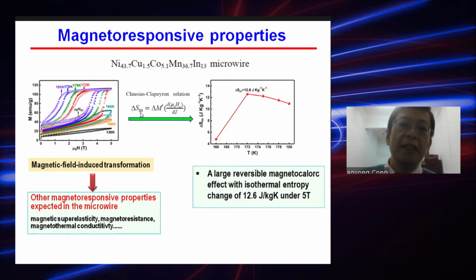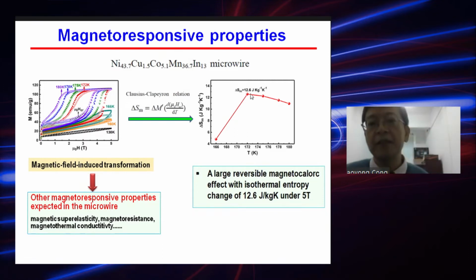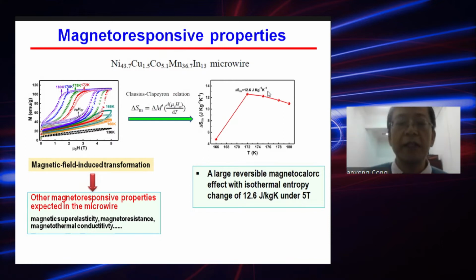We estimated the magnetic entropy change with this equation. We find that under a field of 5 Tesla, we can get a large reversible magnetic field-induced isothermal entropy change of 12.6 J per kilogram per Kelvin.